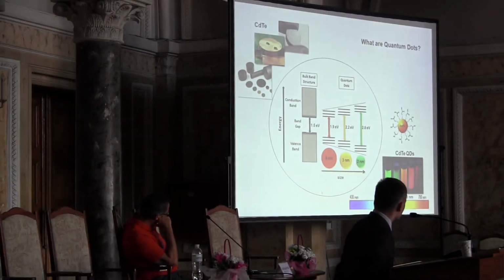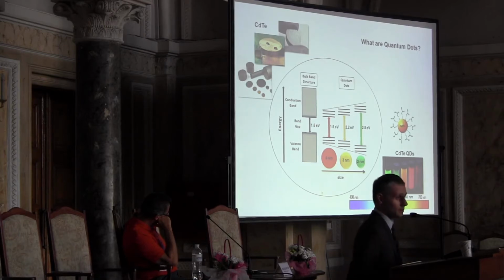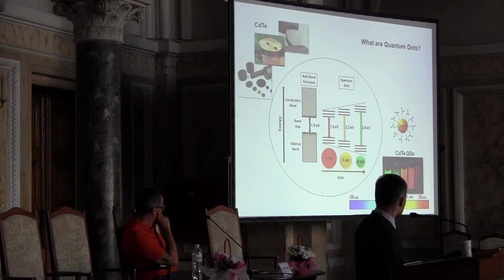If you look at cadmium telluride, for example, which is black and has an energy gap around 1.5 electron volts in the bulk, when we make it small enough, less than 7 nanometers, let's say, we observe quantum size effects. Especially you can look at this graph: if we have 4 nanometer large particles, they will be red in color, and they will also show red luminescence, for example. If you make them even 1 nanometer smaller, they turn to yellow, and even smaller particles go to blue. So basically what you can cover with those materials is this part of the spectrum quite easily.